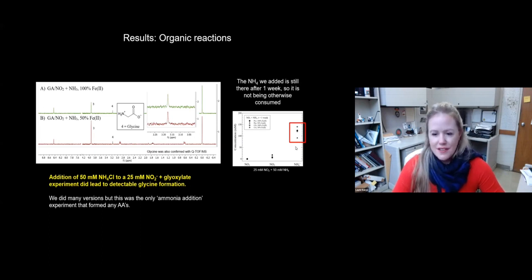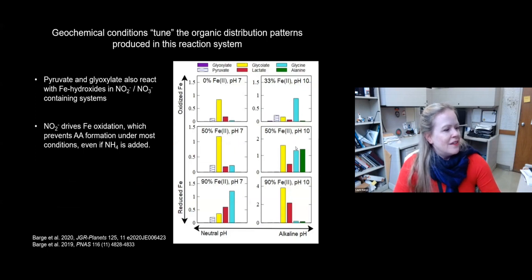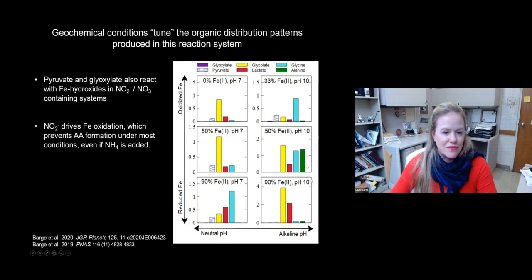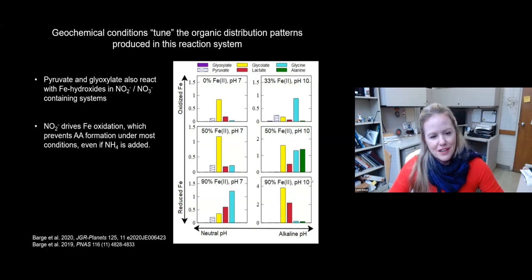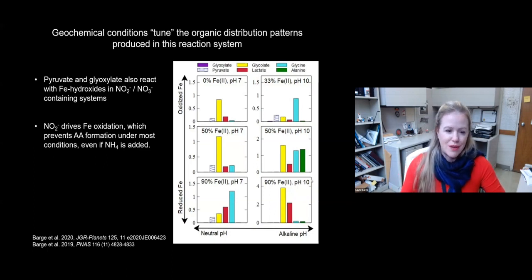So this is interesting because why is this happening? And what is really the effect of the nitrate and the nitrite on this reaction? Looking back at this chart, we can see that you don't really form very many amino acids in very oxidized iron mineral systems, with the exception of some glycine, but only at pH 10. And alanine never formed when the iron mineral was completely oxidized. We also observed that the pyruvate and glyoxylate reacted with the iron mineral to make their reduced products sometimes, but they never made the amino acid.